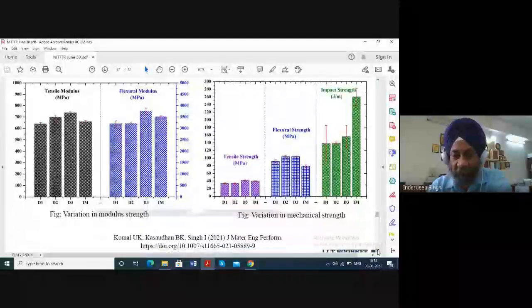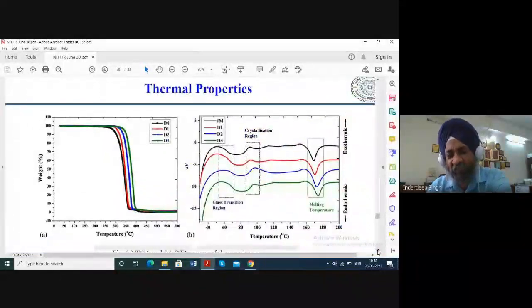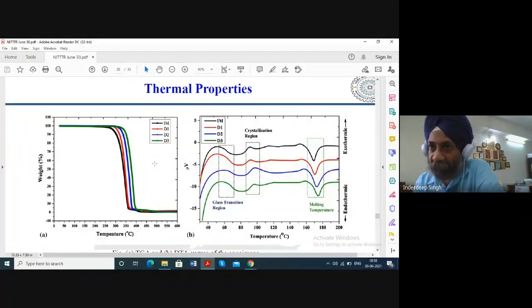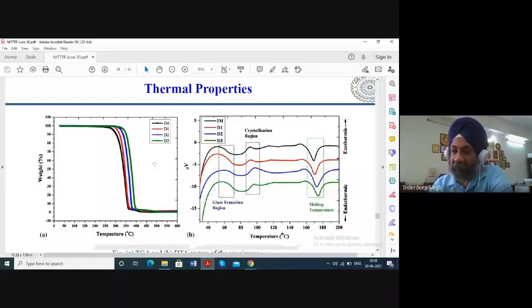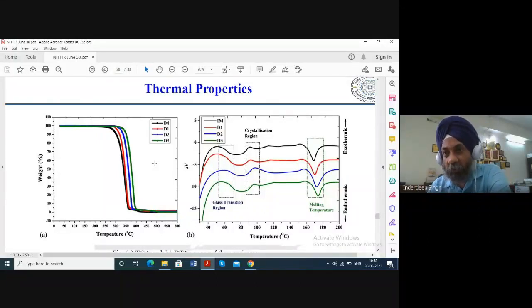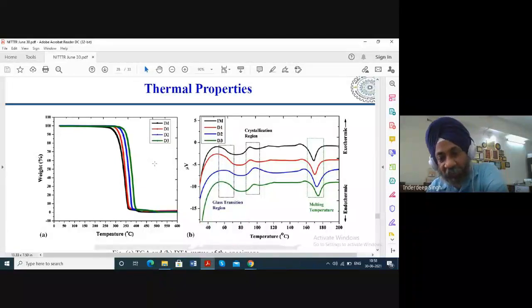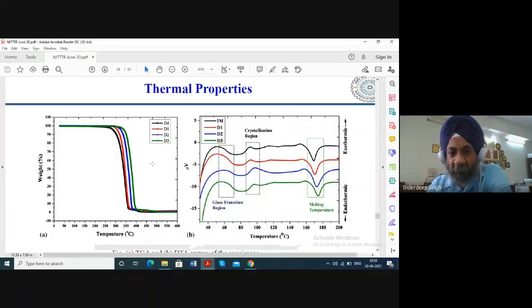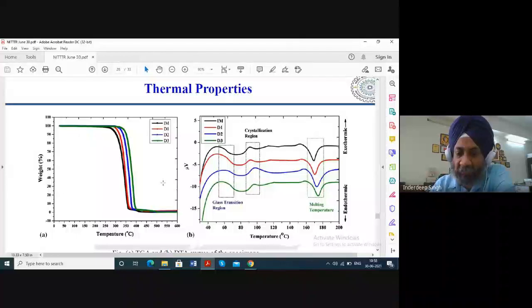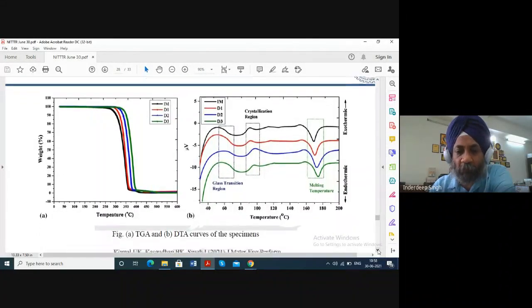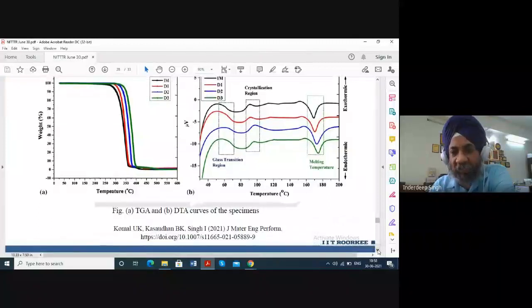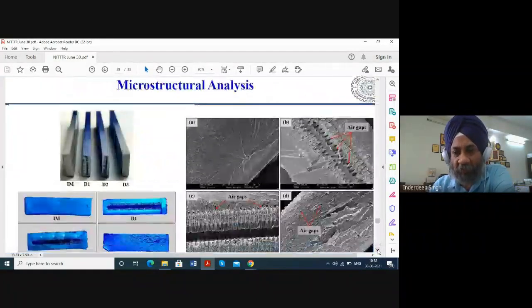So we have variation in modulus. Then we studied how the thermal properties will change, because all the processes are thermal based processes. Because in case of injection molding also, heating and cooling of material is taking place. In case of FDM also, heating and cooling of material is taking place. But there was not much significant difference in the mechanical properties or the thermal behavior of the material. So we studied the TGA and the DTA, but didn't find much gap.